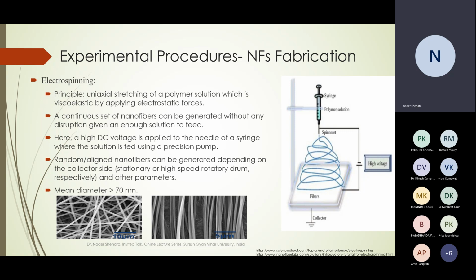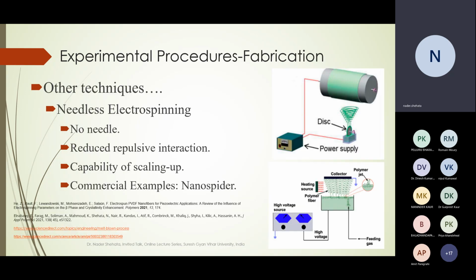Here, the diameter of such nanofibers in different literature, most likely will not be less than 70 nanometers, and it's open range up to micron scale. There are other techniques as well compared to electrospinning, which could be helpful in the formation of quite larger scale nanofibers, because one of the worst disadvantages of the electrospinning technique, whether in PVDF formation or in other polymers, is related to the relatively low scale of the generated nanofiber mats.